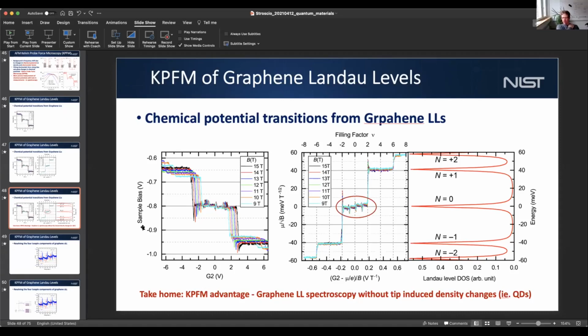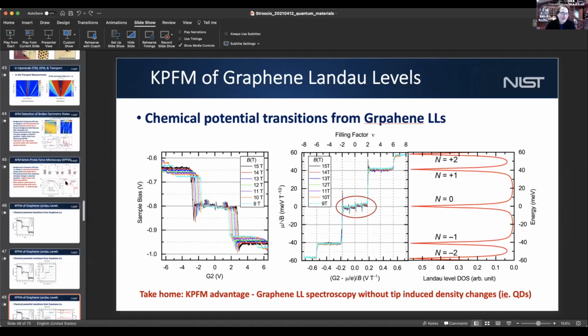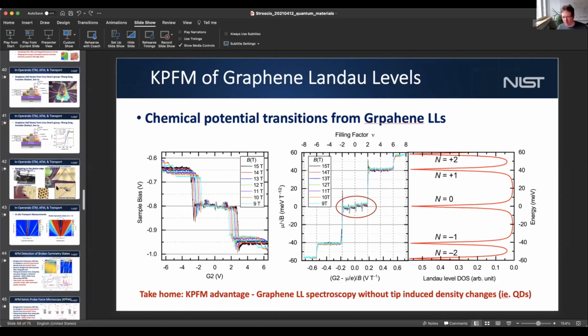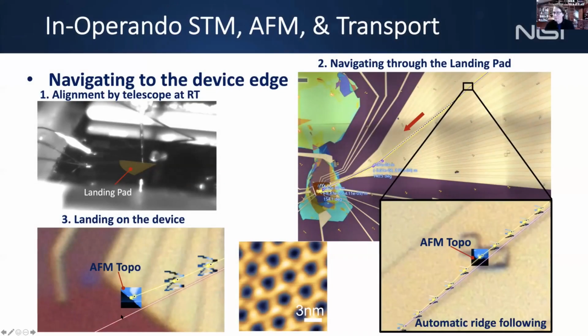There was also a question in the chat from Alexis Baratov. I can read it out. Was the graphene one monolayer in the first part of the talk and two monolayers, or bilayer, with misalignment in the second part? I think he's referring to the Moiré pattern. Sorry if that got confused. This was still a single layer of graphene, and the Moiré here is between the graphene and the underlying HBN insulator, but that still breaks sublattice symmetry and opens up a zero field gap, as shown in transport measurements.